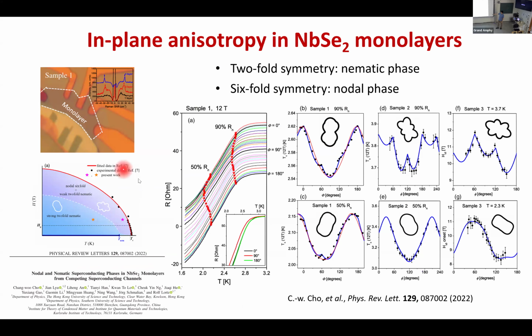So, another group went really down to a monolayer, and in the monolayer they measured how the resistance responds to the in-plane field, also in the transition regime. They claim that around 90% of the transition you see some very weird pictures that look like some kind of six-fold symmetry plus some two-fold symmetry if you plot the response in polar coordinates. Then if you go down to lower temperature, roughly 50% of the transition, it becomes more like two-fold symmetry.